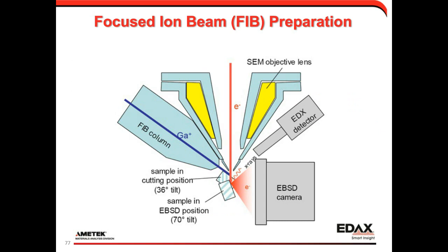We can also use a focused ion beam or a FIB to prepare samples. So in this case, we have a focused beam of gallium ions. We're able to do things like position the sample for milling or cutting, and then position the sample in situ for EBSD. The advantage of this is we're able to prepare the sample in vacuum for something that may be reactive to the atmosphere. We're also able to prepare things on a very small localized scale.